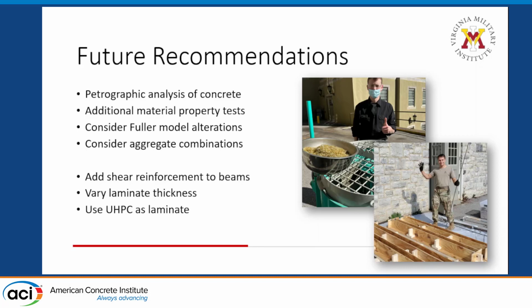The Fuller model, I think, warranted further inspection. This used the finest aggregate, so my thinking was it was going to have the densest packing and the highest compressive strength, but it was actually the weakest. I believe it needed further optimization with the water cement ratio because it did need more water so that I could pour it into the cubic molds. And different aggregate combinations, so Ductal UHPC combines silica fume with crushed quartz and fine sand aggregates, and I think this could be another element to reach a UHPC compressive grade concrete locally.